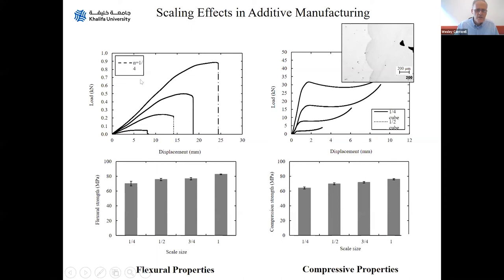Please excuse my legend has disappeared, but this is quarter, half, three quarters, and full scale. But with our flexural strength, there are some size effect issues as we increase our specimen size. Also with our compression strength, these are on various sizes, four sizes of compression sample. And I think this is probably due to the fact that we get defects in these samples. These defects are the same size in all of our scaled samples. So they have a greater impact in smaller scale samples because their relative size is that much larger. And also the edge, the surfaces of our samples as well. That's likely to have a greater impact in our smaller samples than it is in our much larger structures.